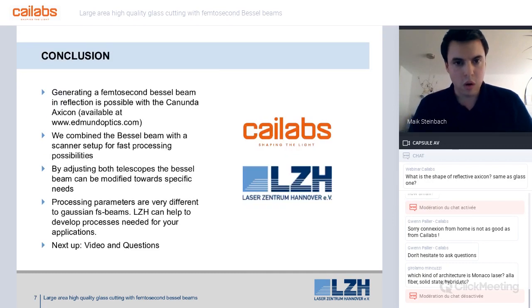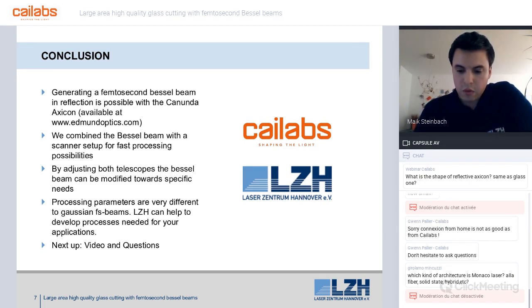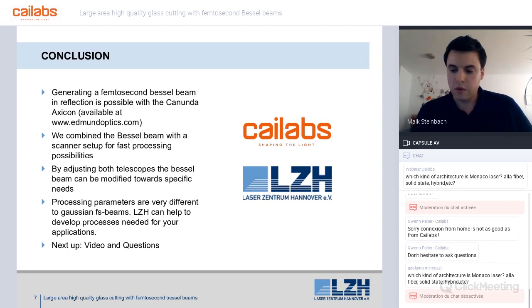Okay, so here's a small conclusion. In this webinar, we showed that generating femtosecond Bessel beams in reflection is possible with a reflective AXICON. The reflective AXICON was combined with a laser scanner for fast processing possibilities. The Bessel beam shape can be modified towards your needs by adjusting the telescope setups. And processing tests showed that it's not so simple to find the correct laser and Bessel beam parameters in order to get a very good quality. More experience and tests are needed.